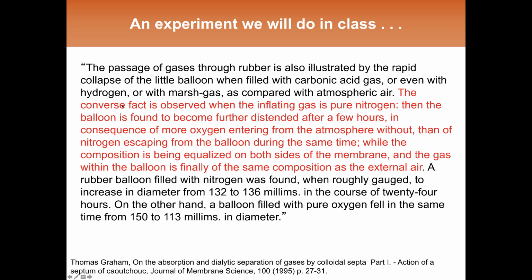And this is the experiment that we'll do in class. Graham observed that if he took a balloon and filled it with pure nitrogen and put it out in air, the balloon was found to become further distended, that it swells after a few hours in consequence of more oxygen entering from the atmosphere than nitrogen escaping from the balloon during the same time.